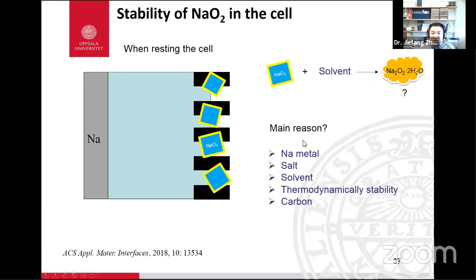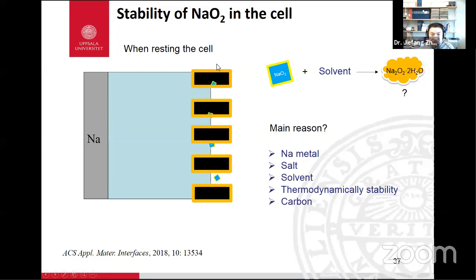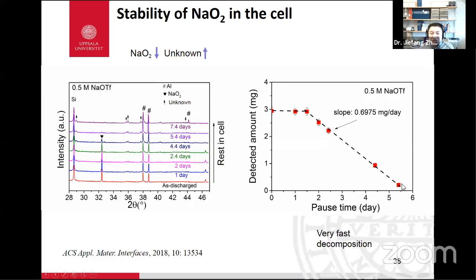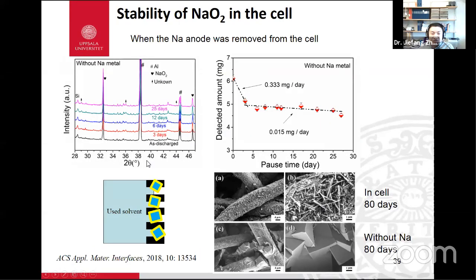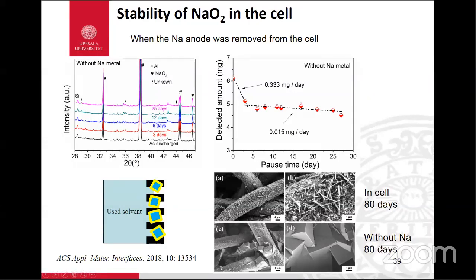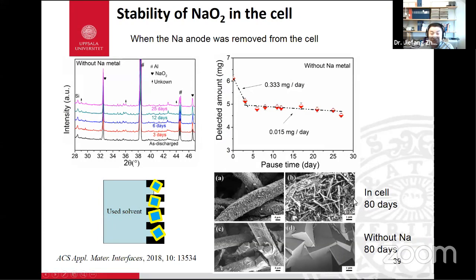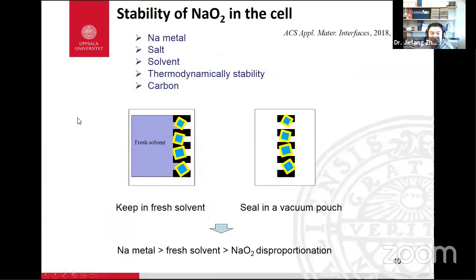So this is another example, a stability study of sodium superoxide in the sodium oxygen battery. We found that after discharge of the sodium superoxide battery, it self-decomposed. Then we listed the possible reasons for this self-decomposition, and we could see that the self-decomposition is actually quite fast. If we remove the sodium metal, even after 80 days we still see sodium superoxide, but with the existence of sodium, we could see nothing. So that's the main reason for the decomposition.